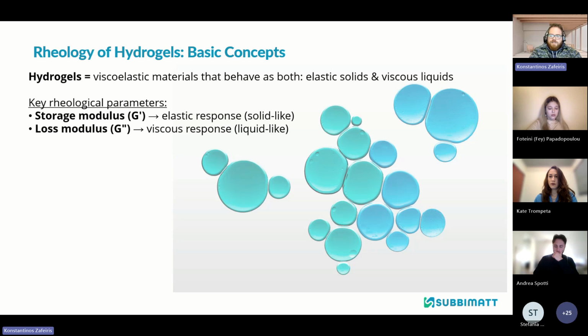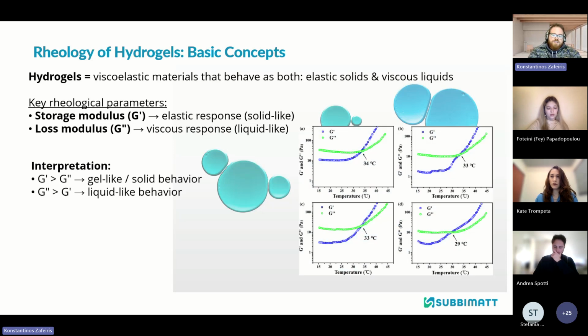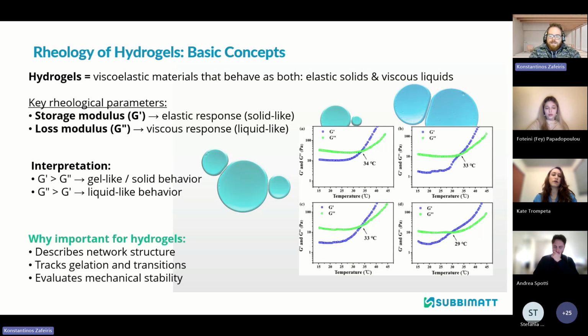Now back to the hydrogel part. Hydrogels are viscoelastic materials, meaning they exhibit both solid-like and liquid-like behavior. This behavior is quantified using two key parameters: the storage modulus, G prime in brief, which represents the elastic or solid-like response, and the loss modulus, G double prime, which represents the viscous or liquid-like response. When the storage modulus is higher than the loss modulus, the material behaves more like a solid, indicating the presence of a stable network. On the contrary, when the loss modulus dominates, the material behaves more like a liquid. These parameters are particularly important for hydrogels as they allow us to understand their internal structure, monitor transitions such as gelation, and of course evaluate their mechanical stability under different conditions.